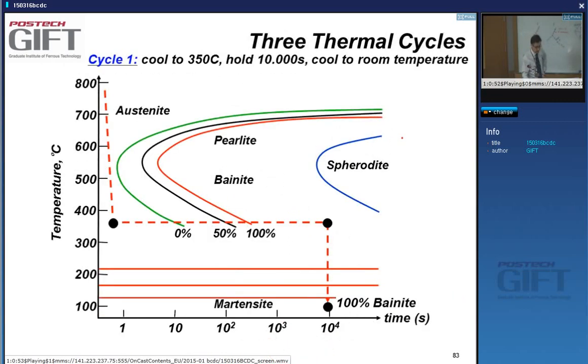All right. Let's have a look at how we can make steels by playing around with the kinetics of the transformation. Remember, when we transform steels, we have the C curves for the nucleation and growth type of transformation, and then the horizontal lines for athermal time independent transformation or decomposition to martensite. Where these curves are and how they are shaped is composition dependent, and the position of these parallel lines is composition dependent.